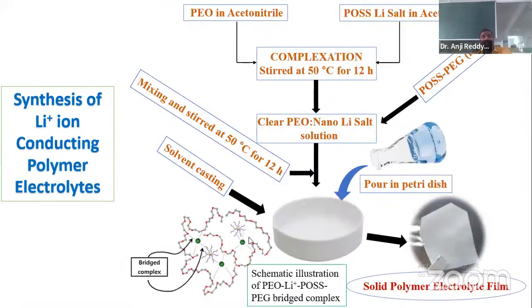And by using those things, we synthesize the polymer electrolytes: PEO, POSS lithium salt, and by adding POSS-PEG of chain length 4. You can observe the film, how good it is. After adding this plasticizer, the POSS-PEG hybrid nanoparticles, the film strength is very good.